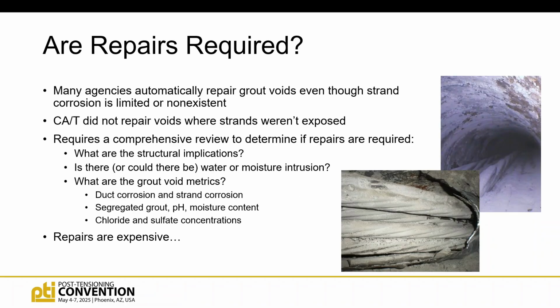So are repairs required? In general, my mentor, Mark Moore, would say, I would rather have the duct fully grouted than not. I think I align with that viewpoint, but there are times when you either can't grout it or it's been determined that they don't need to grout it. When we were working on the Central Artery and Tunnel project, the Big Dig, we learned that when they had voids in their ducts and the strands were not exposed, they elected not to grout those strands. Whereas many DOTs that I've worked with, if there is a void, they are going to fill it. But you may not actually need to, depending on certain exposure conditions.